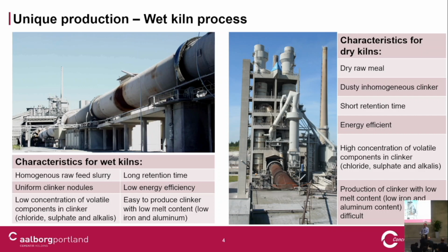And we have no iron in white cement, no iron in white clinker. And in our special clinker, we have a low C3A. And that's only possible because of the wet kilns.